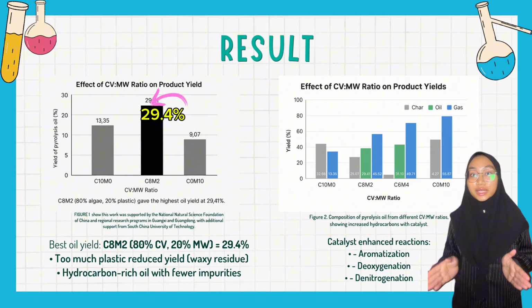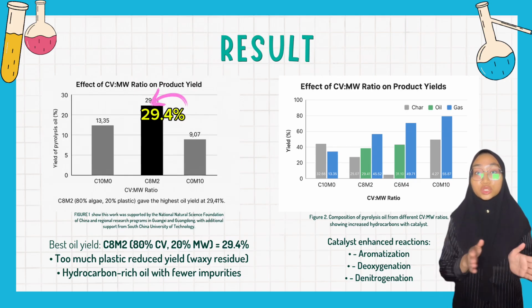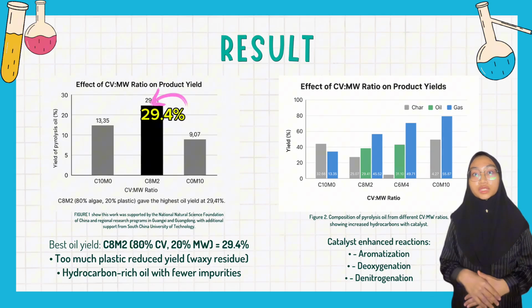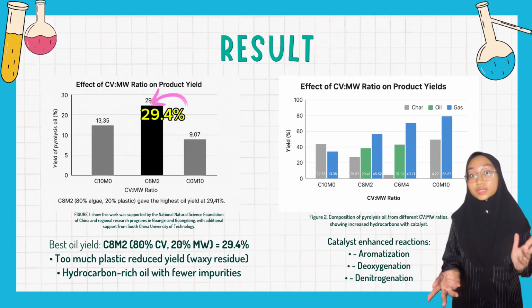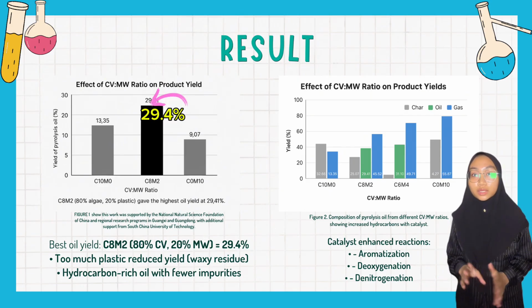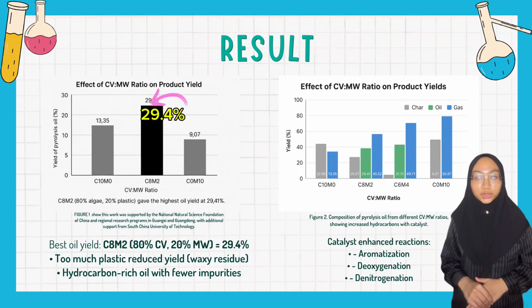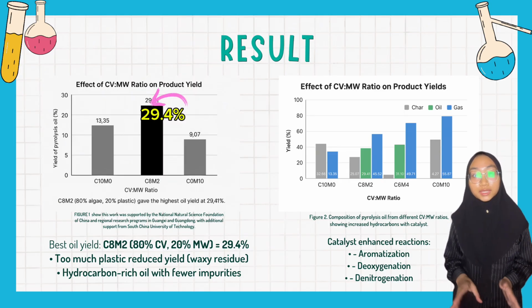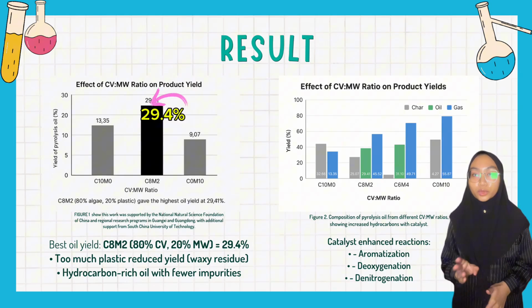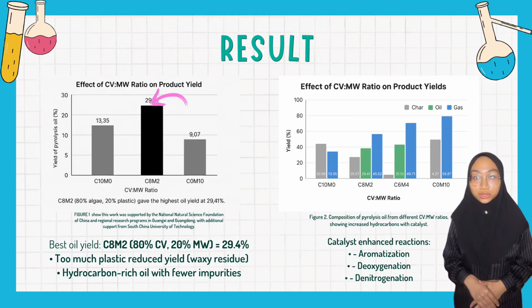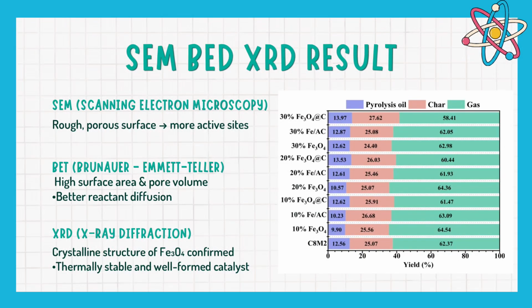This suggests that a balanced mix is crucial, and too much of either component can disrupt the synergy. The presence of the catalyst also increased the proportion of desirable aromatic hydrocarbons in the oil, which are important for energy applications. To better understand the catalyst, we use SEM, BET, and XRD analysis.